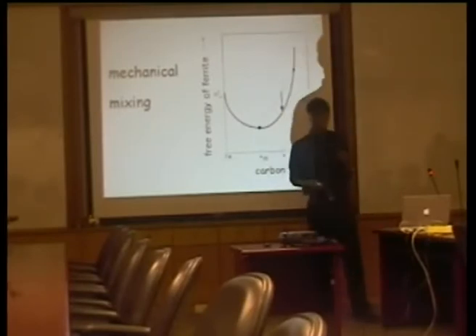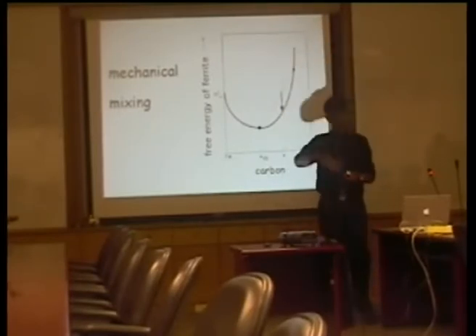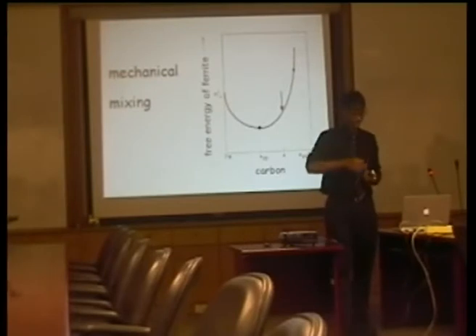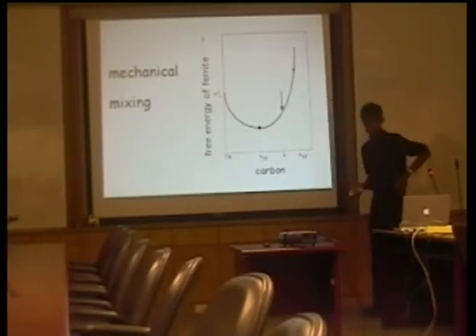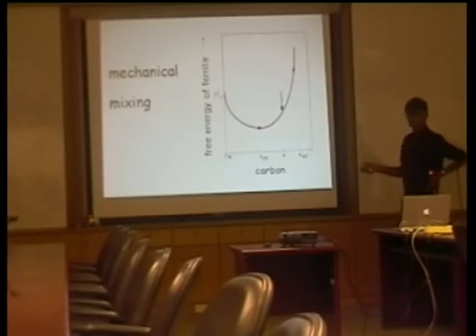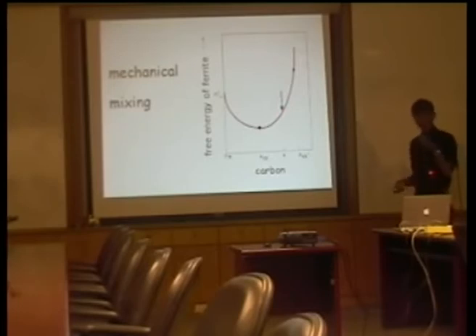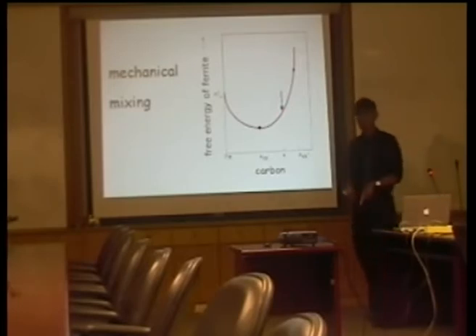If we look at the free energy of body-centered cubic iron, here we are plotting the free energy of ferrite against the carbon concentration. This is the starting ferrite, and this is the martensite with a much higher carbon concentration. What this diagram shows is that if I mix them up, then I actually get a reduction in free energy.